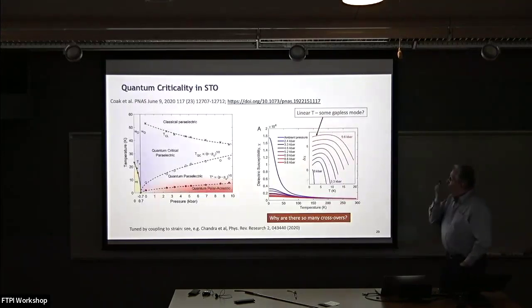A little bit more look at that phase diagram, and this is data from the Cambridge group, which is actually under pressure. So this is a temperature-pressure plot. And here, if you like, you're looking at the dielectric susceptibility, and at ambient pressure you see that this diverges, or almost diverges. However, if you put the system under pressure, you move away from the quantum critical point and this saturates. But if you look closely in the vicinity of there, there's a whole bunch of crossovers.